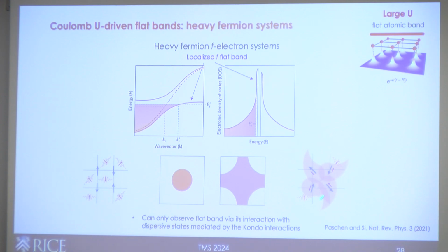And if you turn on, for example, Coulomb interactions between the localized moments and all these conduction electrons, then you start to see the flat band in the form of hybridization between the flat band and the dispersive band. So the bands you will see are like this guy and this guy. So then you start to see some spectral weight from the flat bands. And then the size of your Fermi surface under this construct will also change.